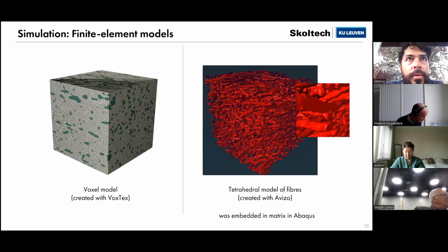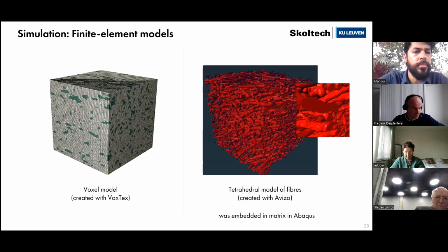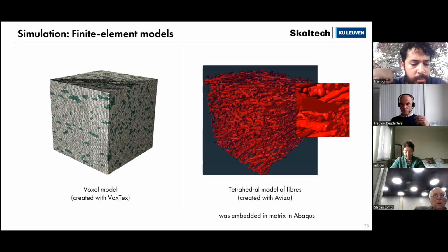So for example, if the microstructure of your material is more complex, how would you change the VoxTex parameters then? Yeah, if the material were more complex and, for example, had much smaller, more curved fibers, I would decrease the distance between voxels, and I would relatively decrease the window of integration of a structure tensor inside VoxTex software. So I just would make the voxel size smaller.